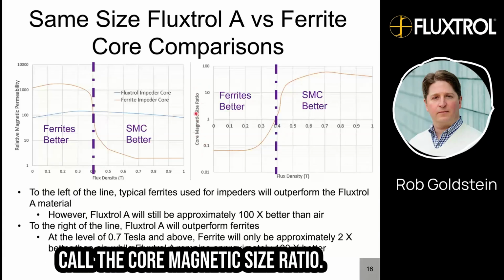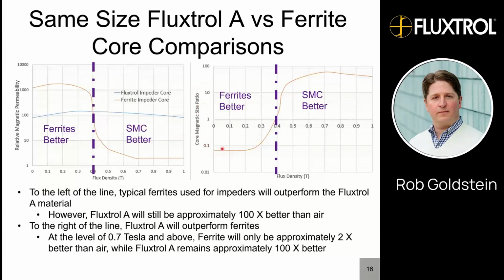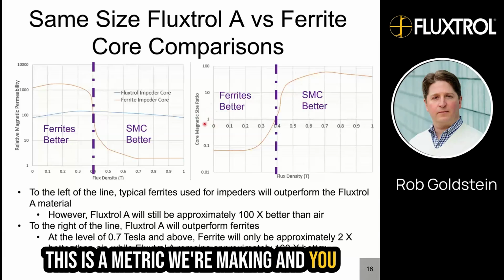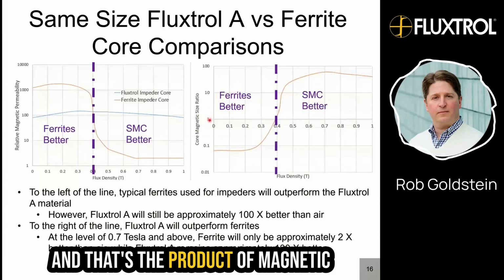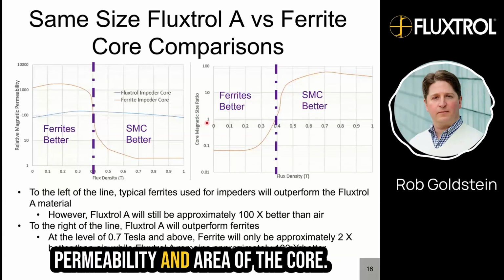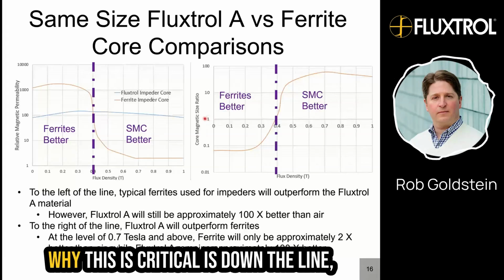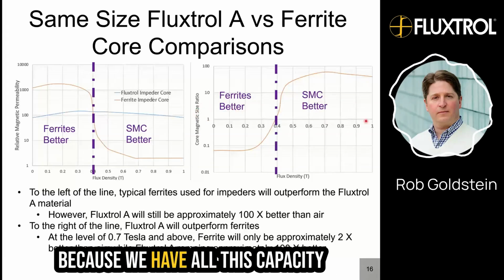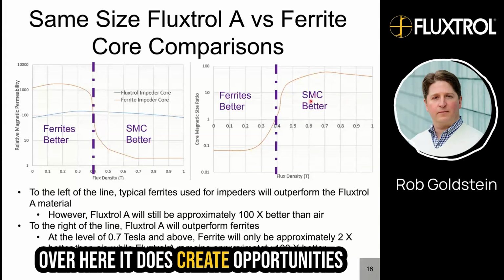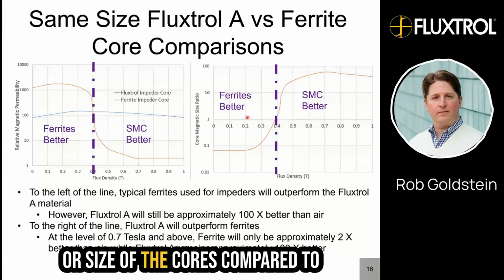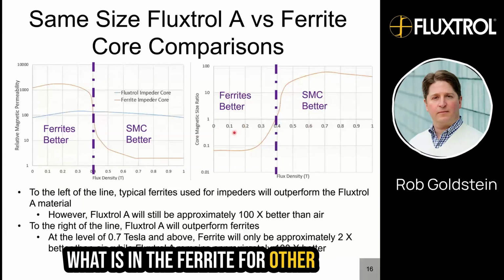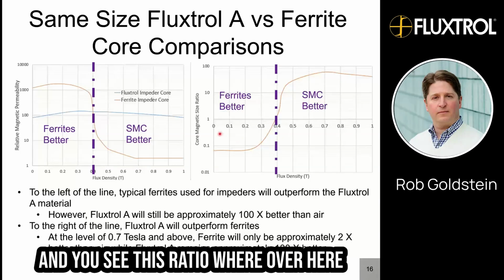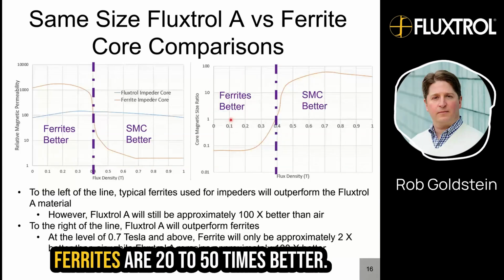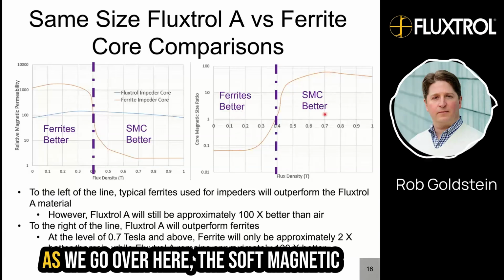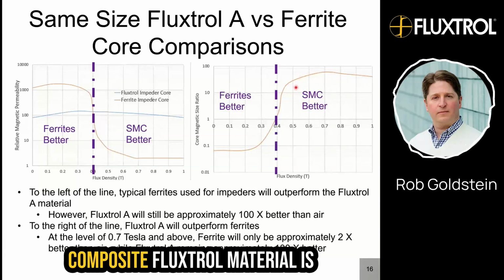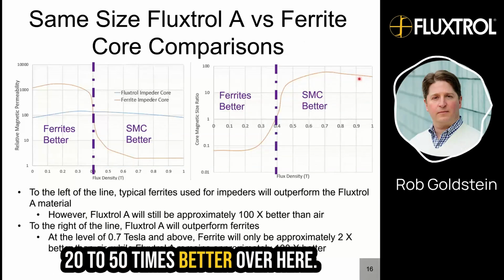Another way to look at it is what I call the core magnetic size ratio. This is a metric we're making, where you could look at that value being 1, and that's the product of magnetic permeability and area of the core. Why this is critical down the line is that because we have all this capacity over here, it creates opportunities to use different shapes or sizes of cores compared to the ferrite, for other reasons, and to improve a system. When you see this ratio, over here ferrites are 20 to 50 times better, and as we go over here, the soft magnetic composite Fluxtrol material is 20 to 50 times better.